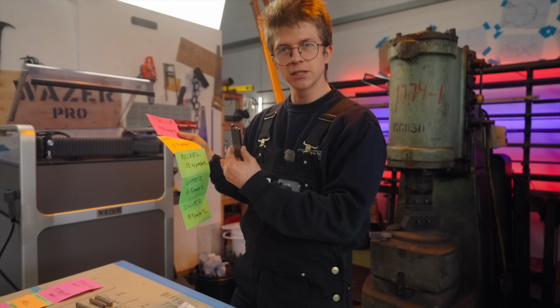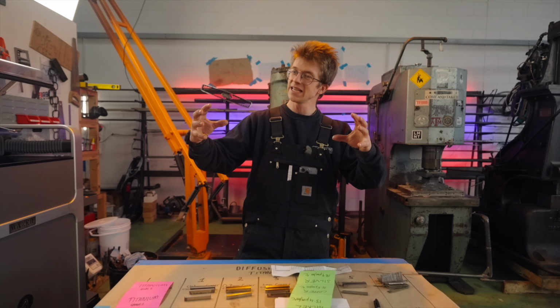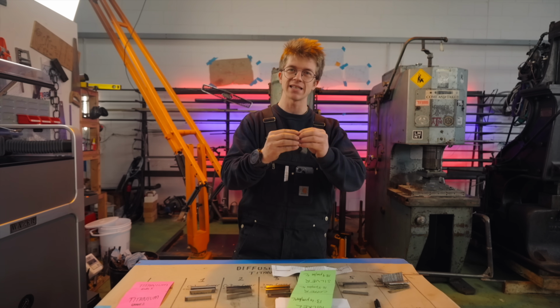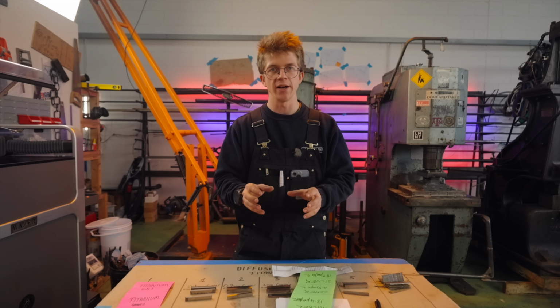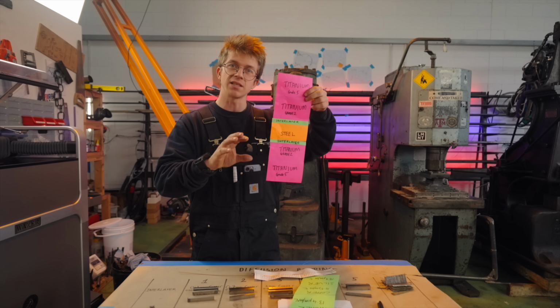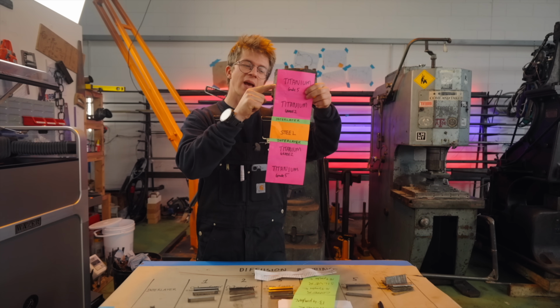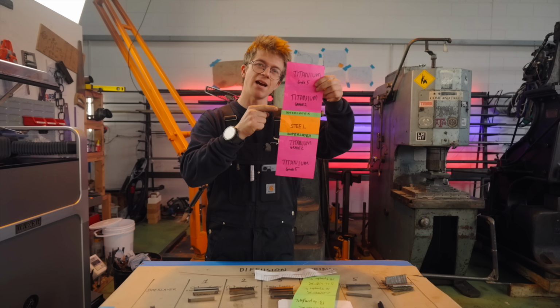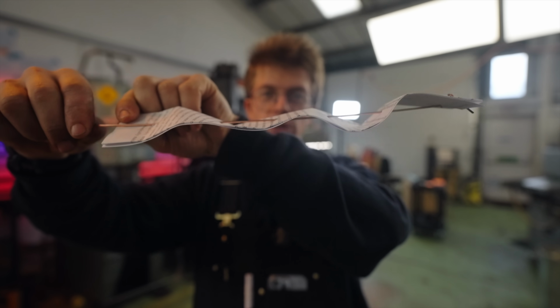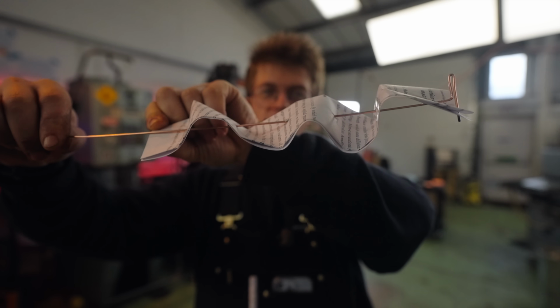So all the stuff in our delightful sandwich is expanding as it gets hot and contracting as it gets cool at a different rate to one another. And so perhaps as we heat up our billet and weld it, the titanium hasn't expanded as much as the steel and the interlayer, and then once it's bonded and proceeds to cool, the titanium is being pulled from both sides as the steel and interlayer shrinks more than it, forcing this sinusoidal wave into our materials.